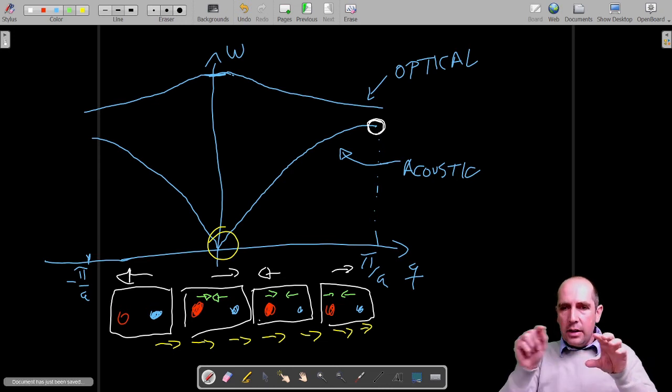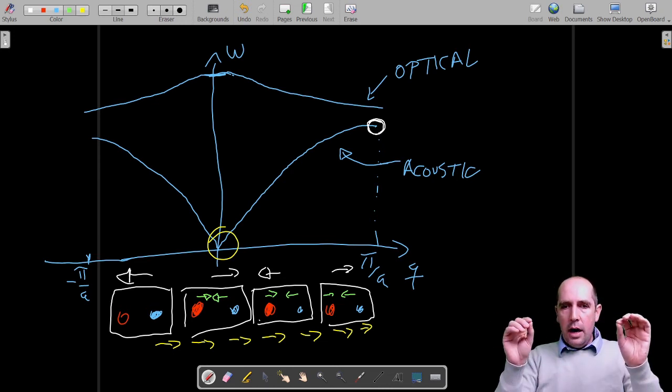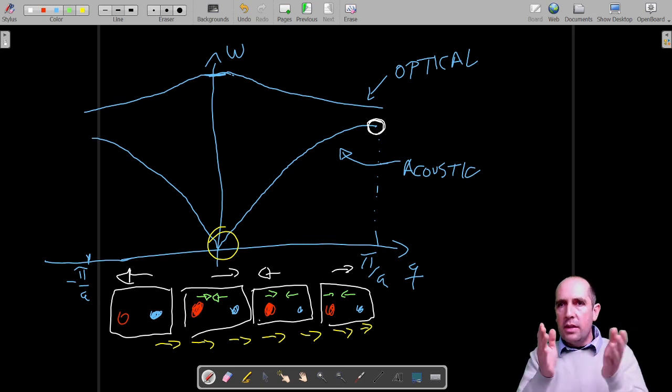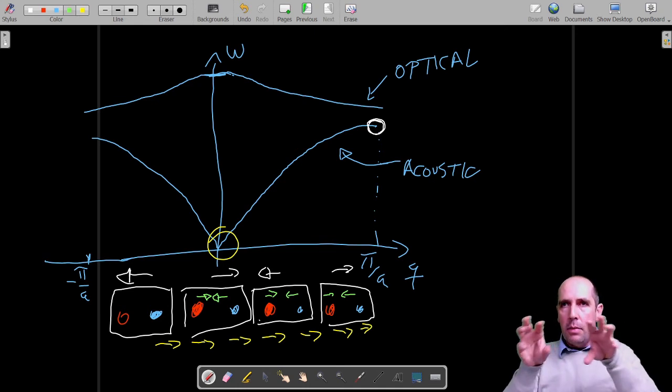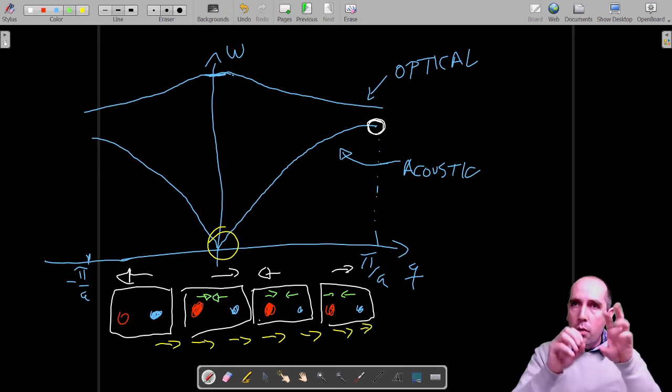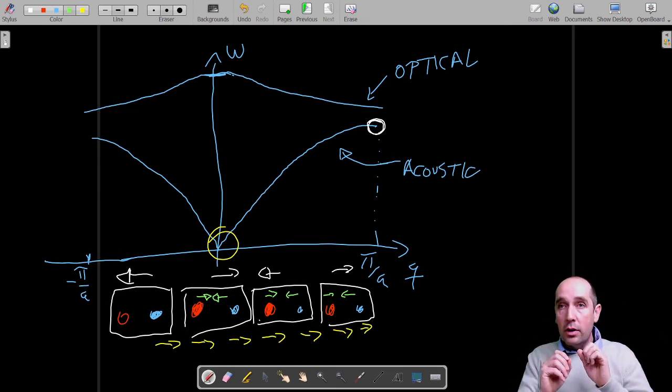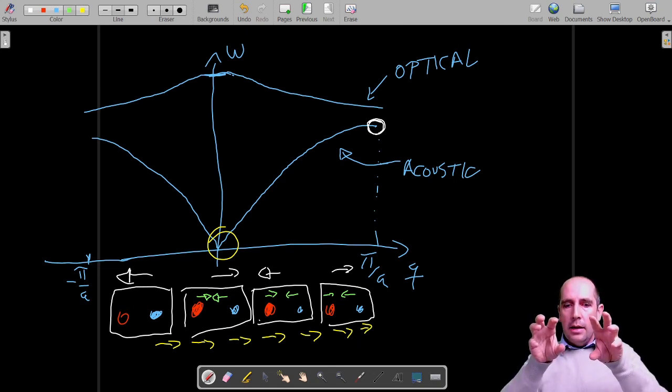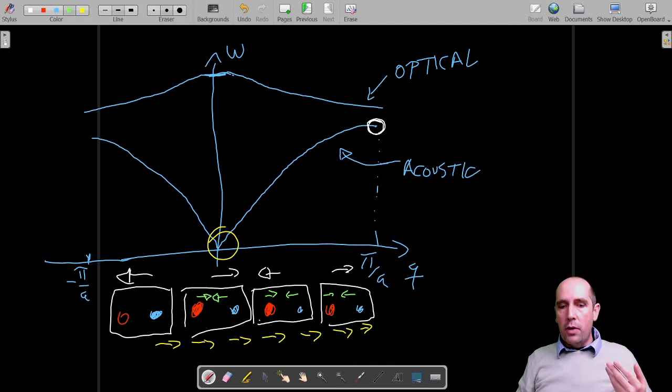So if we just have identical atoms in a straight line, we cannot distinguish between them, and therefore there is no charge distribution between one atom and the next one. But if we have two types of atoms, one could be a bit more positively charged and the other one a bit more negatively charged, depending on how electrons are arranged and so on. And in that case, electromagnetic radiation can produce these vibrations. So it can introduce the vibration of the lattice.